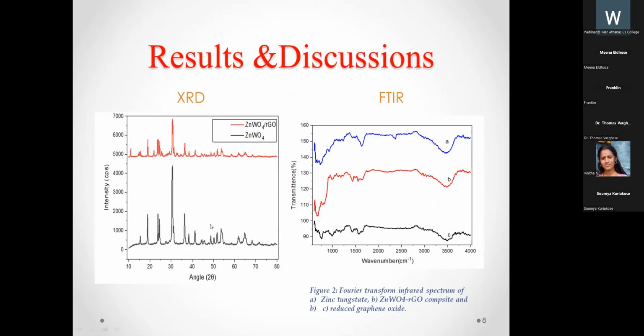It is clear that the intensity of the zinc tungstate peaks has been reduced, and the crystallinity has also changed to some amorphous character. Here we are modifying with about 4% of RGO at the maximum. In addition to that, an extra peak has appeared for the reduced graphene oxide at a 2 theta of about 23 degrees.